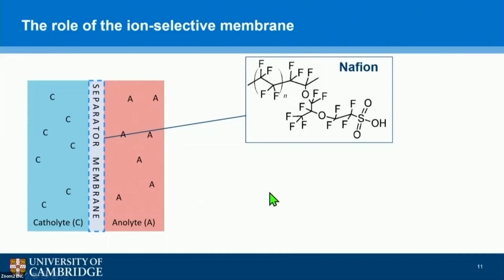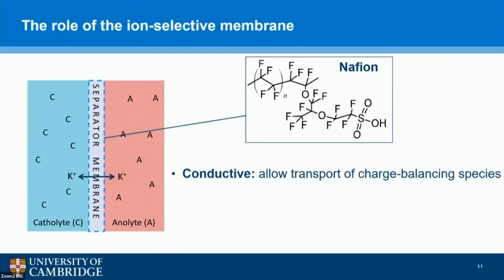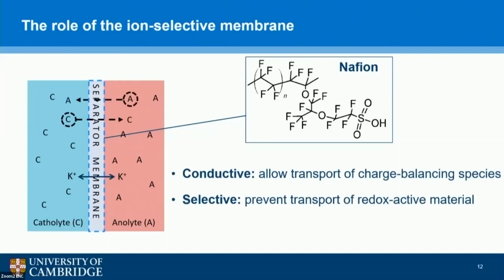And this basically works by, we lose this proton here when we're in a basic solution, so we have a negatively charged sulfonate group. What we want is for the membrane to be conductive so that we can maintain electroneutrality, but we also want it to be selective, because if we have crossover of this redox active material, we just lose capacity in the battery. This is termed crossover.